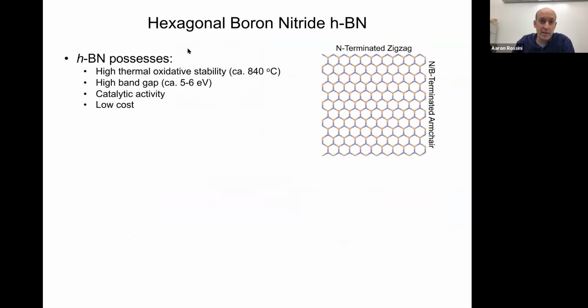One material that we got interested in studying was hexagonal boron nitride. This has a very similar structure to graphene or graphite, where you're going to have this honeycomb structure. In this case, rather than having carbon atoms, we have these alternating boron and nitrogen atoms that make up the honeycomb. The reason we got interested in studying this material is because we actually have a collaborator, Ive Hermans' group at Madison, Wisconsin, and they are using hexagonal boron nitride as a catalyst for the oxidative dehydrogenation of alkanes to alkenes.